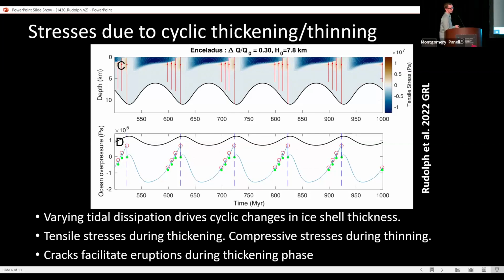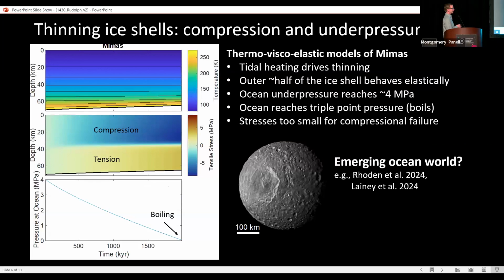We also include a model for tensile failure here, and under some circumstances, during the thickening phase of ice shell evolution, we find that it was possible for tensile cracks to connect the surface all the way to the subsurface ocean, perhaps facilitating eruptions. We argued that this was a feasible mechanism for the initiation of activity at Enceladus South Pole. Here we consider the thinning phase of ice shell evolution.